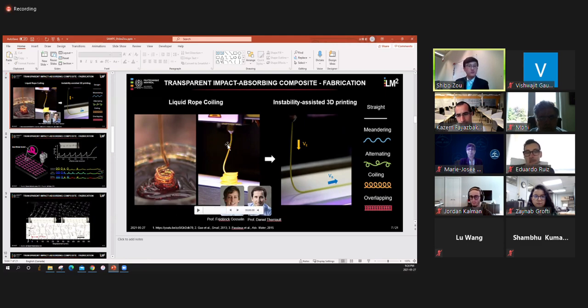So here we are only extruding pure polymer. Actually, if we are talking about fiber in composite materials, mainly that's the filler, the fiber filler that we added into this thermoplastic, so that it's a kind of nano composite. We can add carbon fibers or glass fibers into this material. Actually, we collaborated with a research group in Germany because they have a continuous fiber extrusion FDM 3D printer, where they impregnate the polypropylene, the thermoplastic, around one continuous glass fiber. So that's a continuous glass fiber, continuous fiber reinforcement.